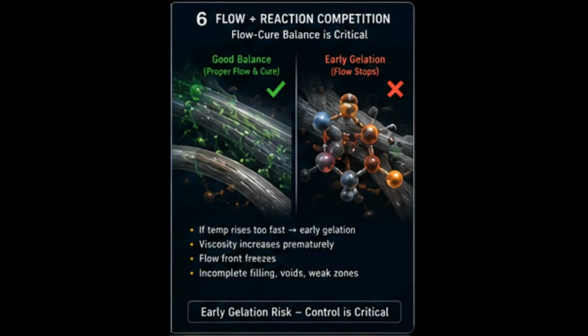The balance between flow and reaction, or cure, is critical. If the temperature rises too fast, it can cause early gelation, which increases viscosity prematurely. This can freeze the flow front, leading to incomplete filling, voids, and weak zones.